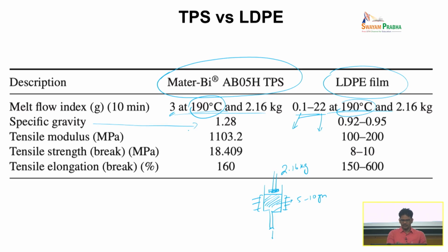Then if you look at the density, clearly the density of TPS is higher because of the crystalline nature and packing, hydrogen bonds, and modulus, if you see, the modulus is actually much higher. So that means you have a much stronger polymer, and you can also see that tensile strength is also high, and the elongation at break is basically on the lower end. So what that means is, as long as you're going to use this polymer for some static application, like you make a bag or you make some sort of wrapper, this is fine.